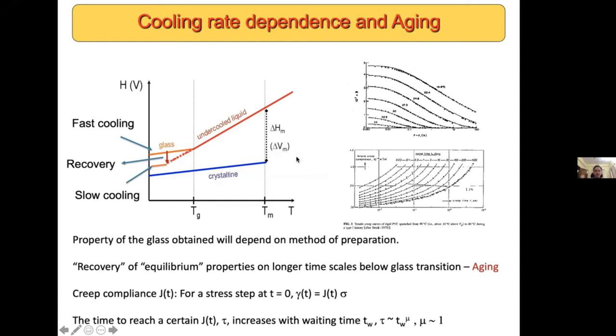the volume or the enthalpy or other properties, where one has an equilibrium regime where there is some behavior that doesn't depend too much on the cooling rate. But below the laboratory glass transition temperature, there's a departure from this liquid-like behavior with a rapid change, or a discontinuity of slope, but a continuity of properties. And the point at which this happens is higher if the cooling rate is higher, and vice versa. So unlike the liquid to crystal transition, which is also depicted here, where the properties would exhibit discontinuous change, the glass transition, if one thinks of it as a phase transition, is a continuous one from a thermodynamic perspective.